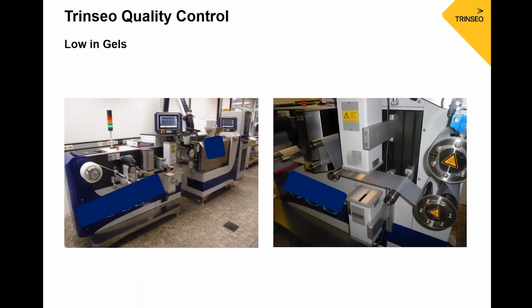This is very important information. So how do we quantify this? We have a quality control process where we extrude a thin film of the material, and there's a camera system set up to count the specific types of gels that we see, the defects in that material, so we can quantify and control what we let out as good quality. So it's very important to be able to test and understand that also.